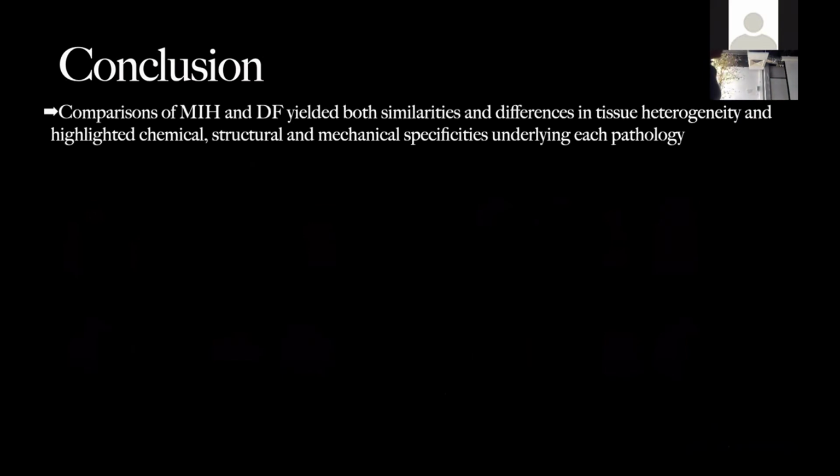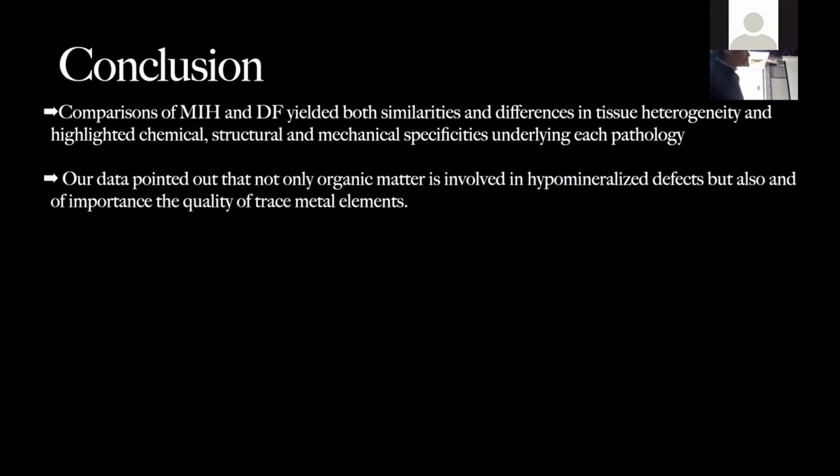To conclude our study, first, the comparisons between MIH and dental fluorosis yielded both similarities and differences in tissue heterogeneity, and highlighted chemical, structural, and mechanical specificities underlying this pathology. And clearly, our data pointed out that not only the organic matter is involved in these hypomineralized defects, but also, and of importance, the quantity and the quality, the type of trace metal or inorganic element play a major role in both pathologies.